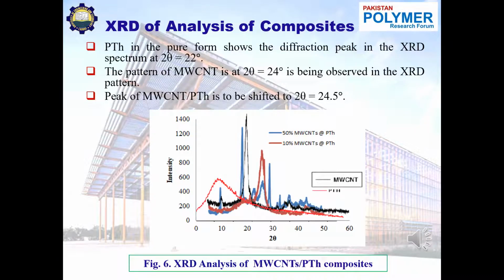XRD diffraction analysis of pure polythiophene, pure MWCNT, and the polythiophene MWCNT nanocomposite was performed in order to measure the crystallinity of the samples. Polythiophene in pure form shows a diffraction peak in the XRD pattern at about 22 degrees. The broader peak shows the amorphous structure of the polymer. The pattern of MWCNT was observed at 24 degrees, a sharp peak, which shows the crystallinity of MWCNT in pure form.